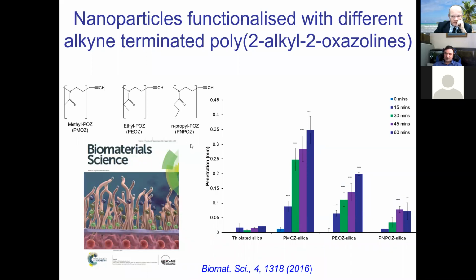And we have conducted another study comparing these systems, and what we've established is that polymethyloxazoline shows the highest enhancement in the diffusivity of these nanoparticles, and N-propyl polyoxazoline is much less efficient, and its efficiency is very comparable to the sticky thiolated silica.